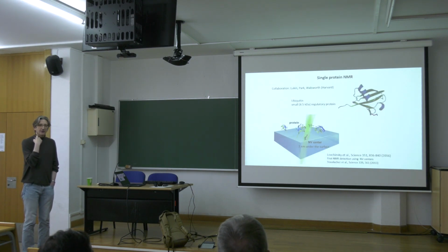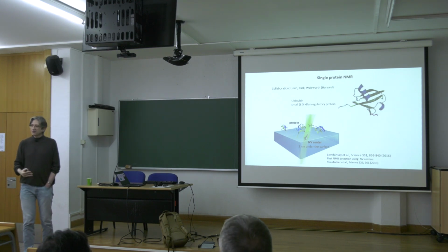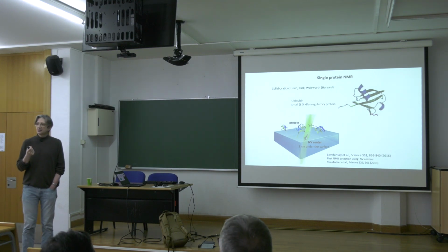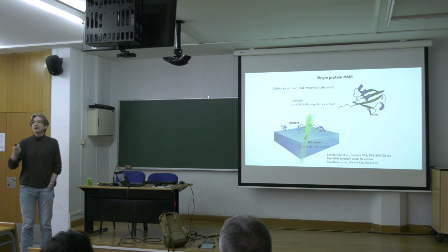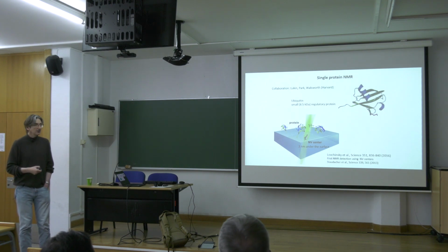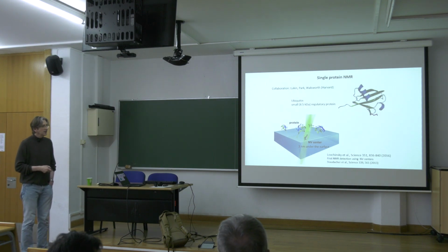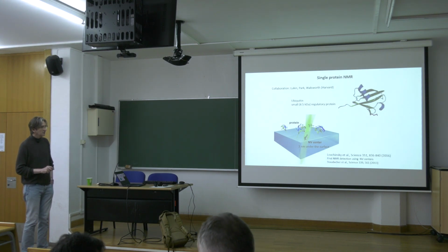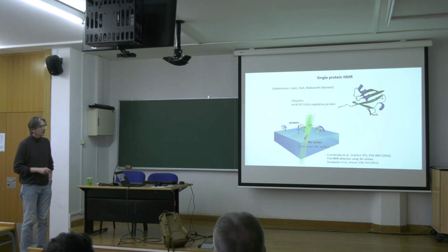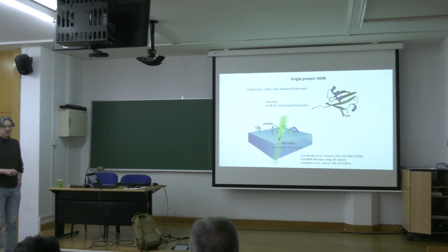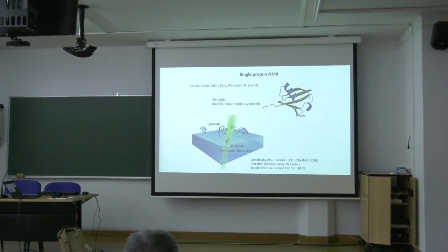An example of applications, there are multiples, but I think one of the most promising ones is to detect magnetic resonance signals coming from spins outside of diamond. I give you one example here. It's an NV center, which is implanted below the surface with this precision of a few nanometers I mentioned before, and the biomolecule was attached to the surface of diamond just above.